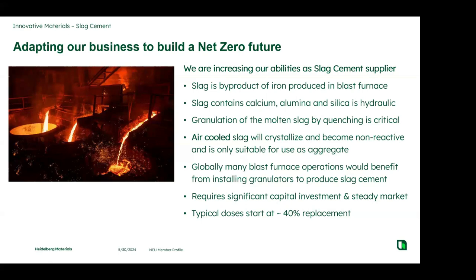For instance, with slag, slag is a waste product from the blast furnaces, like we talked about. You can see the different materials being tapped off from a blast furnace. The slag material needs to be quenched. It's a byproduct from that iron processing in the blast furnace. It has all the right chemistry, but if it's air cooled, slag becomes inert. It's essentially just a stone or something that is often landfilled because it has very little value in the market. It's just a porous rock. Well, if we are quenching these and we install a granulator in some of these blast furnace operations, that then becomes these valuable slag cement materials.